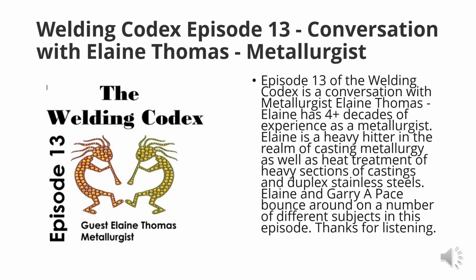And again, the big challenge was getting that nitrogen into the matrix. This made it weldable, castable, formable. It was the big deal with duplexes. Okay, so when we're talking duplex, part of our matrix is austenitic and the other part is ferritic, right? That's correct. The matrix is ferrite, and there are pools, giving us some strength, correct? Correct. You're going to have a strength up around 65 KSI, and some alloys maybe as high as 70 to 75 KSI. The pools are austenite.